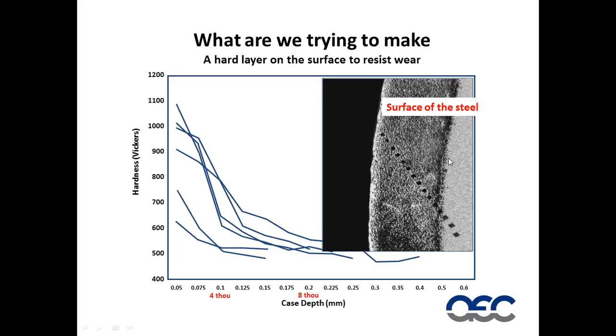And you can see the bigger the size of the dent, like here, the softer the steel is. The harder the steel, the smaller the dent we get. So you can see here at the very surface of this piece of die steel, it's very hard, and underneath it's a little softer. This is represented by these graphs. And you can see the best of these case thicknesses have a Vickers hardness at the surface of around 1,000, dropping to the bulk hardness of the steel, which is around 500 Vickers and equivalent to the mid-40s in Rockwell C. And the case depth is around 6 to 8 thousandths of an inch in depth. And that's what we're trying to achieve.